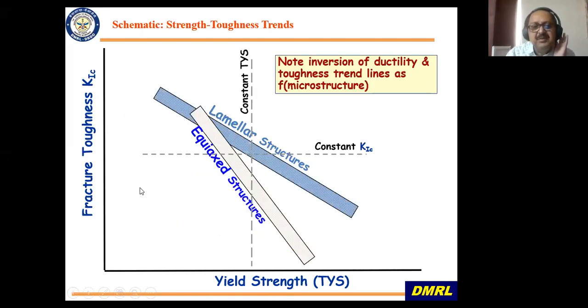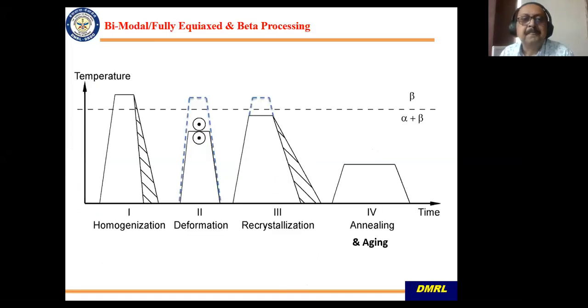Then here I am showing you the fracture toughness versus yield strength. A lamellar structure, that is a beta treated structure, has a higher fracture toughness at similar strength level. An equiaxed microstructure or a bimodal microstructure has much lower fracture toughness as compared to a lamellar structure, which always has a higher fracture toughness. So if you want good fracture toughness, you should go for a beta treatment or should get a lamellar structure.